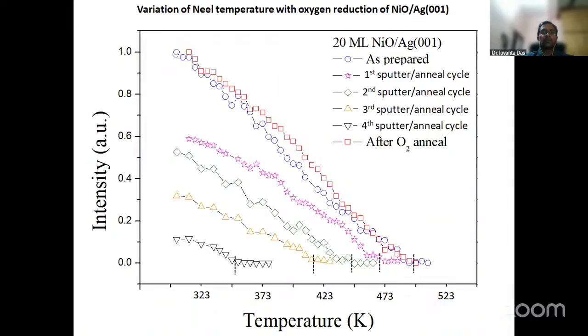Okay, sir. And when we did the LEED studies with temperature variation, we could observe the half-order intensity variation with temperature, and we could determine the TN values for these samples. And as you can see, these are the first, second, third and fourth argon ion sputtered samples, and these are the results I am showing. And when we oxygen anneal the sample, we can get back a similar result as the as-prepared film. So this stoichiometric variation can recover itself with oxygen annealing.